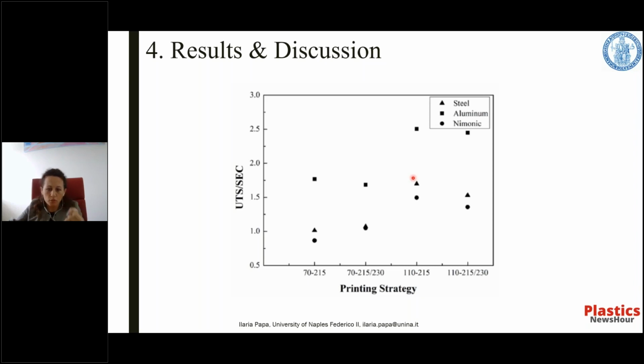There exists a linear correlation between the SEC and the printing time, as expected, and so a new efficiency index, given by the ratio between UTS, that is the tensile strength of the component printed, and SEC, was evaluated. The index explains numerically how high a tensile strength is obtained per unit of specific energy consumption in the FDM process. So a higher value of this ratio indicates a better process efficiency for the printing strategy. And this figure shows the variation of this efficiency index by varying the printing strategies reported on the x-axis.